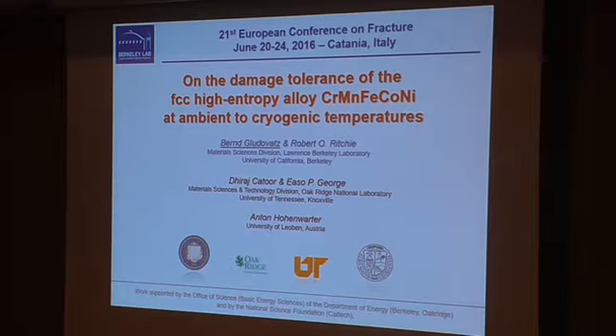We have done some EDX analysis though and found that they are either chromium-rich or manganese-rich. We think that they are oxides from processing of the material, which is quite common, particularly as manganese is known to be very keen on oxygen. And when we take manganese out, then this oxide and these particles disappear to a large extent.